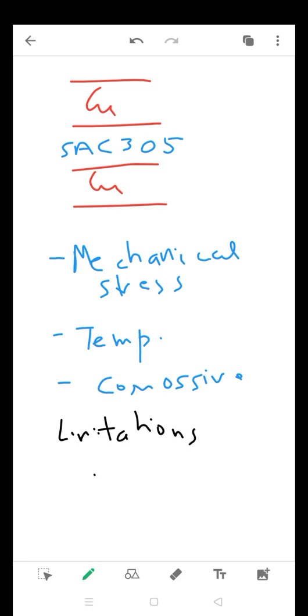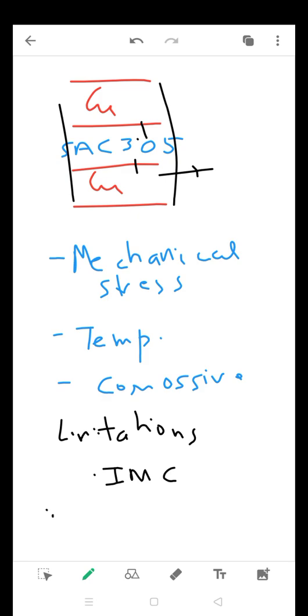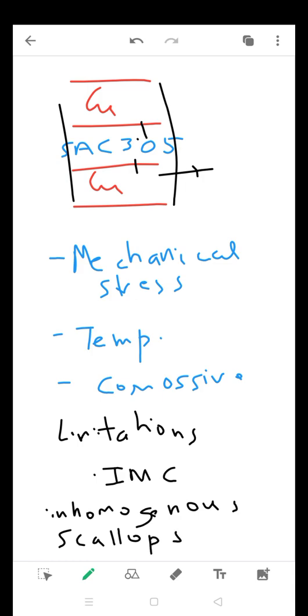Limitations include formation of something called an IMC. IMC stands for intermetallic compounds. Now, as we are joining these substances, a lot of chemical reactions will take place in this solder joint and at the interfaces. These chemical reactions will cause something called inhomogeneous distribution of intermetallic compounds, and there is formation of scallops, that is, inhomogeneous distribution of the different phases formed.